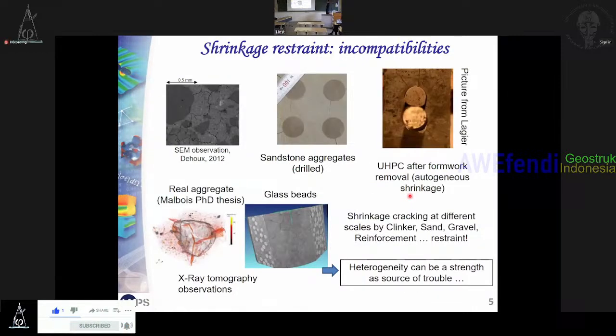But also, do not forget that we are working on reinforced concrete structures, and that we have cement paste and aggregates. And we have an important mismatch between all the phases. So for instance, if you look at the scale of aggregates, most of the time, except some light aggregates or natural aggregates, you have almost no shrinkage inside the aggregates, only in the cement paste. So the shrinkage of the cement paste is restrained by the aggregates. So it gives rise to cracking inside the specimen.